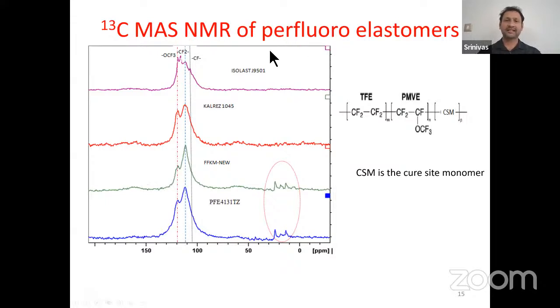Here we have done C13 NMR of the perfluoroelastomer that is used in our launch vehicle. We found that this system is composed of tetrafluoroethylene and this perfluoromethyl vinyl ether (PMVE). Here you can see three different peaks, from which you can find out what the M and N repeating units are. By deconvoluting each peak, you can also find out the ratio of these peaks, that is, how much is the CF2 system and how much is the other system in our O-ring.